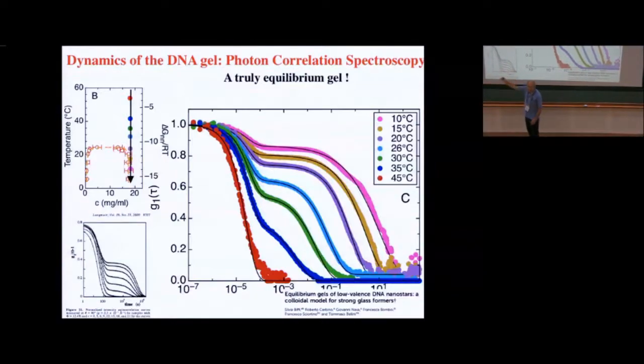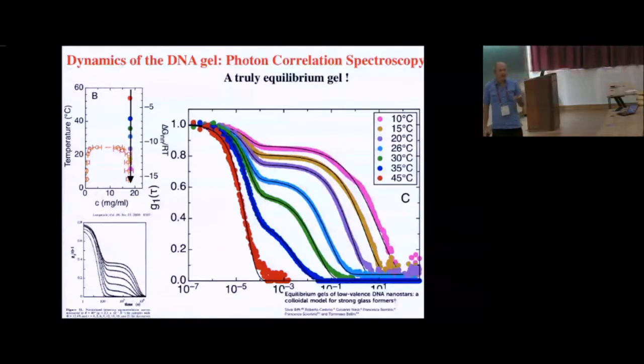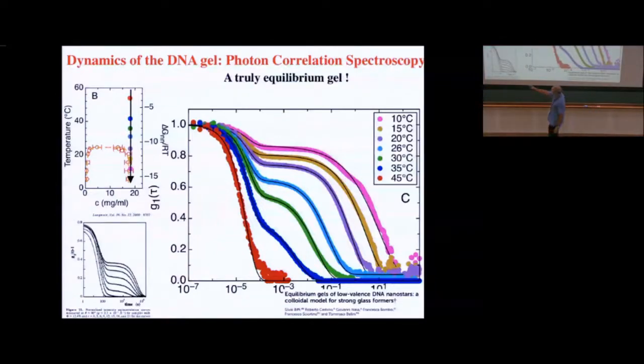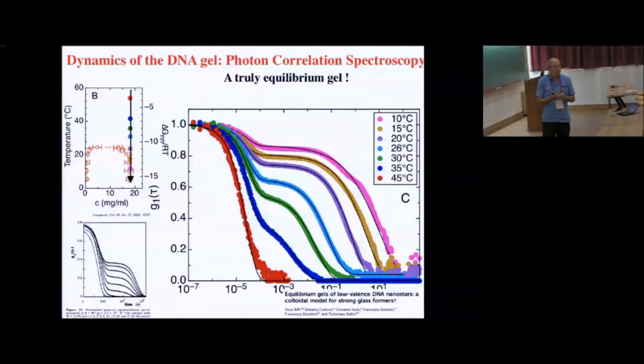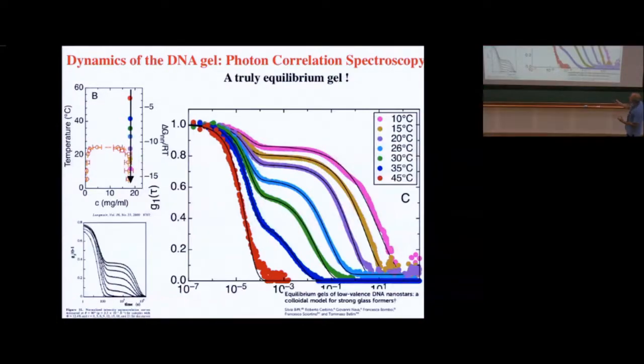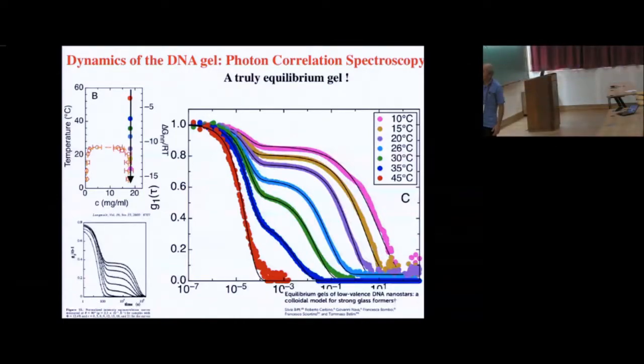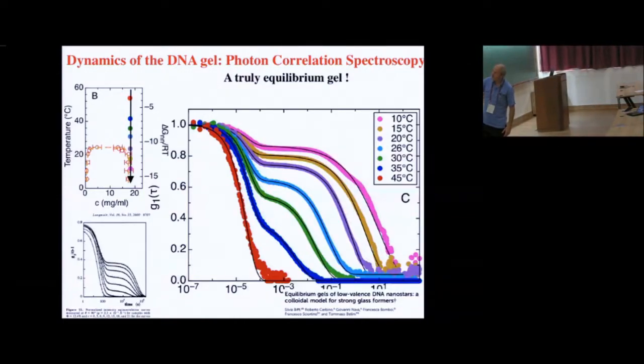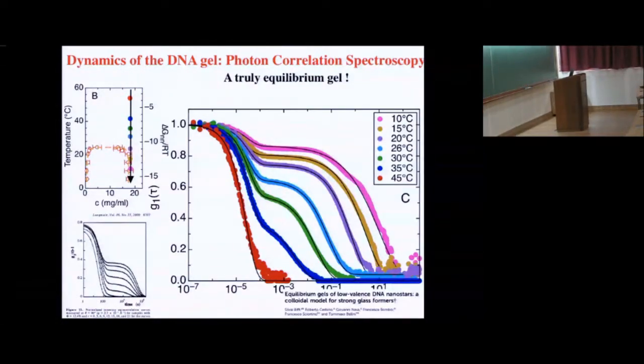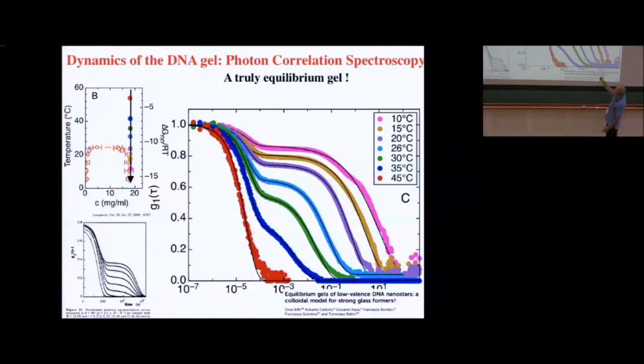Now here, the decay of the density fluctuation comes from the fact that the head of the polymer evaporates and finds another droplet where to go. And this is a time which is always the same. It does not depend on temperature. So the alpha relaxation time is always the same. In our case, we have a DNA-DNA bond that controls the strength of the interaction between the particles. And this bond becomes stronger on cooling because there is a free energy of binding due to the sequence of the DNA. And so our system becomes slower and slower on cooling due to this increase in the strength of the bond. So we have both physics: the formation of the gel, and then the lifetime of the bond gets longer and longer, and this slows down the alpha relaxation dynamics.